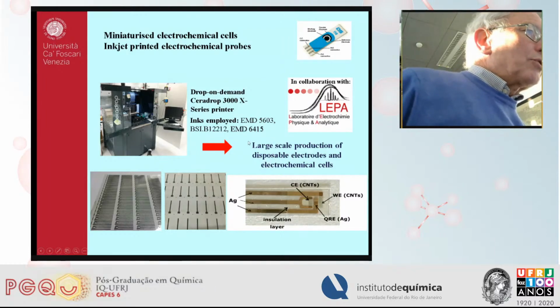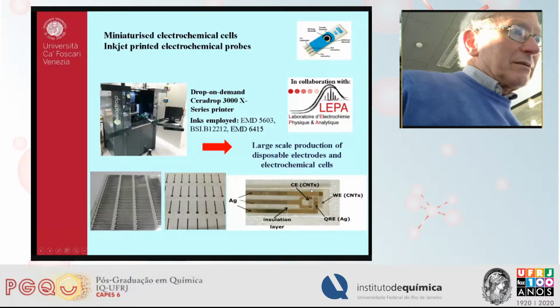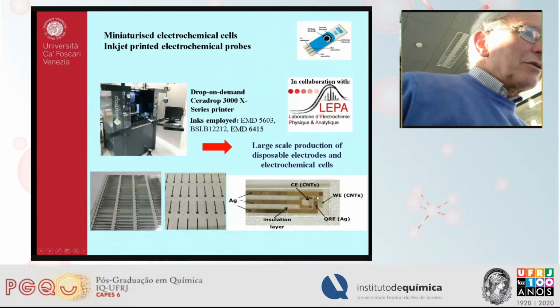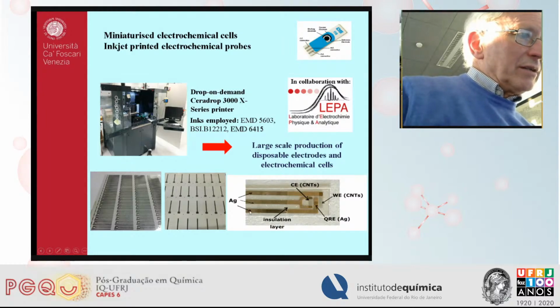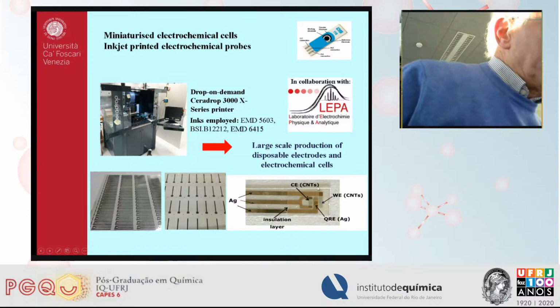electrochemical cells, we try, by using this kind of inks, to construct a small cell like this one. And here are shown the materials with which these are composed. We have a silver reference electrode, a working electrode which is made by carbon nanotubes, and a counter electrode also made by carbon nanotubes, but this electrode, the counter electrode, has a much bigger surface area.